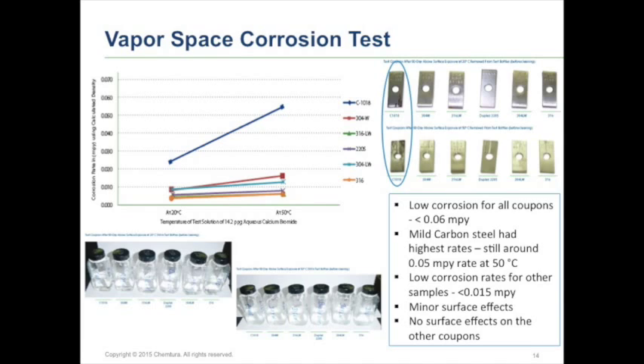But for the most part, when you look at the corrosion, in the vapor space test here, the carbon steel was the one that really demonstrated the most issue. And even so, that's still around 0.05 mils per year as far as corrosion. So still fairly low in most cases. When you break out this lower piece to the bottom graph, you can see that for the most part, these are all still very low corrosion rates. Definitely with a little bit of temperature, as you would expect, you get a little higher corrosion rate. And then the surface impact here, I know that's probably a little bit difficult to see, but for the most part, the carbon steel was the only one that really demonstrated any kind of major pitting or any other corrosion evidence.